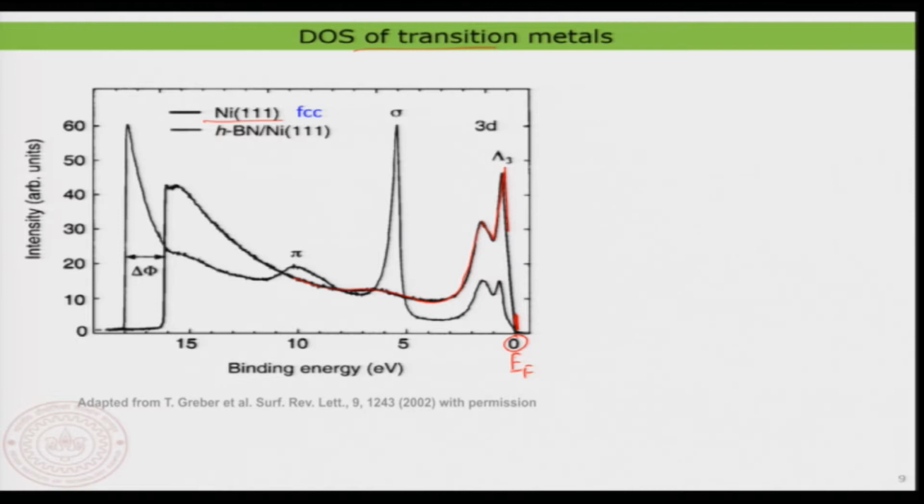For example, gold is known to be a noble metal because the corrugation in the density of state is quite flat near the Fermi energy. Any electron close to the Fermi energy is the one having the lowest binding energy, and that is the electron capable of being involved in a chemical reaction when the surface is exposed to something.